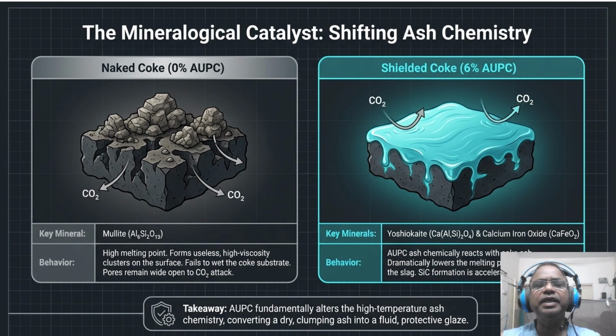The AUPC ash reacts with the coke ash to dramatically lower the melting point and viscosity of the slag. So we are essentially converting a dry abrasive ash into a fluid protective glaze that can actually move and cover the surface. And that glaze leads us to the most critical physical process on the coke surface, that is ash wetting.